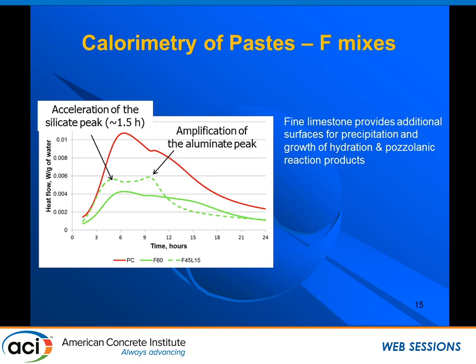So first we have the silicate peak for the PC mix in red and the aluminate peak. When we put in fly ash, there's a shift to the right—that's the delayed setting, and the peaks are much lower. When we put in limestone, we amplify the aluminate peak and shift the curve to the left, helping with setting time, because the limestone provides nucleation sites.